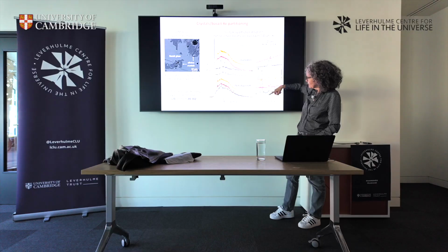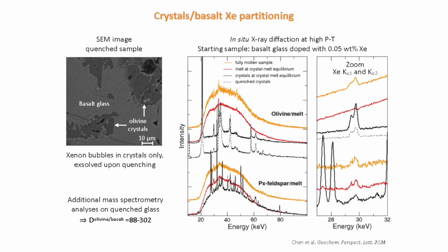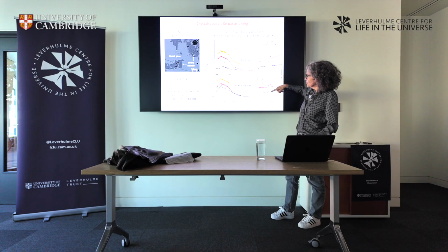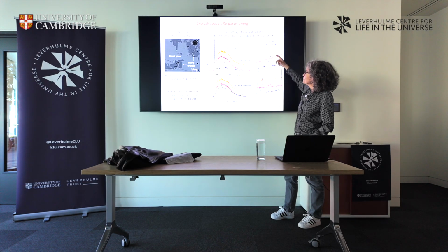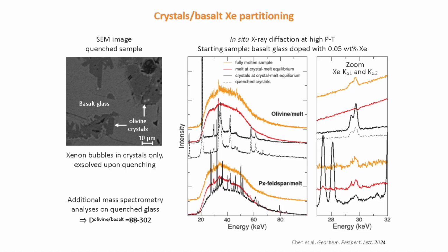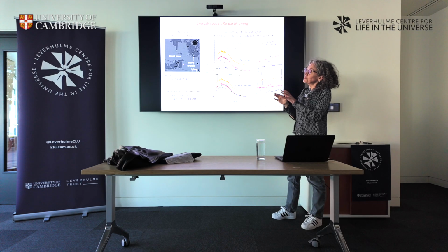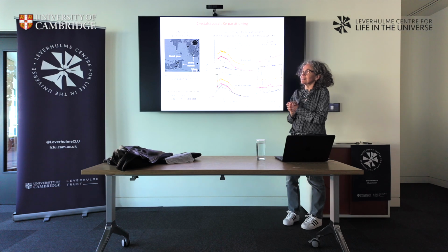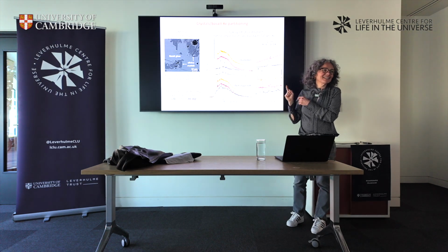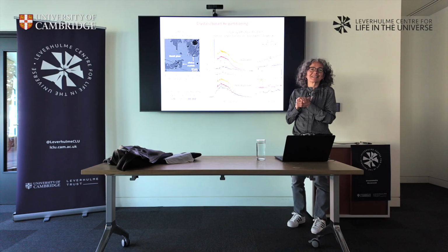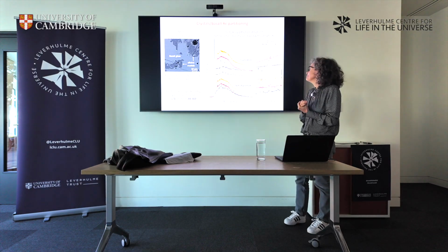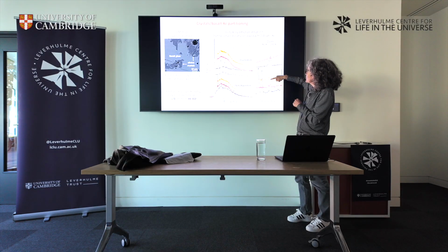So first look at the bottom, which was a mix of pyroxene, feldspar, and melt. There is more xenon in the melt than in the crystals, but in the olivine, it was the other way around. In the olivine, that's the initial glass. So we start from a glass, which is doped in xenon, a very tiny bit of xenon. We try to put as little as possible because then geochemists tell us it's not realistic. You don't have parts per trillion, but we need to see something. So we need to put more. But anyway, that's the best we can do to be able to detect something.